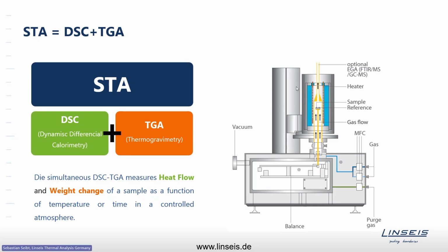The blue part up here is insulation material, and the red part you can see next to the insulation is the heater that surrounds the inner sample chamber. The configuration here has an open furnace, so the gas exhaust is on top, but you also have the same setup with the gas exhaust at the flange down here. So either you have a gas flow coming from the sample gas in here into the furnace, going out at the top, or it gets in here and gets out at the flange directly.